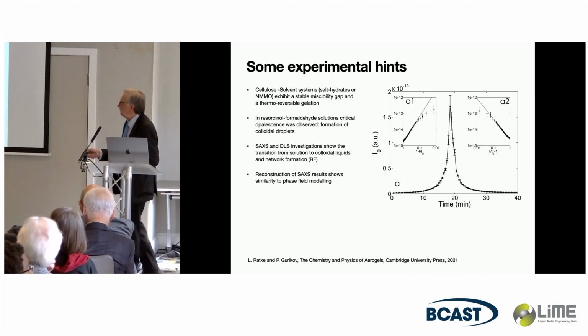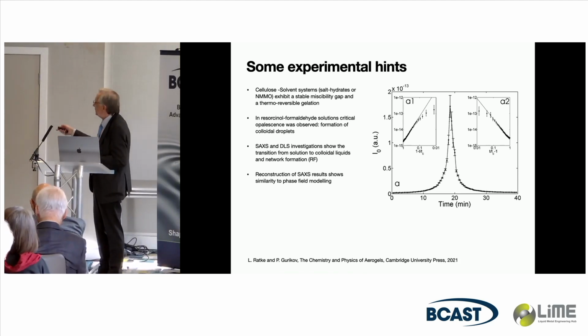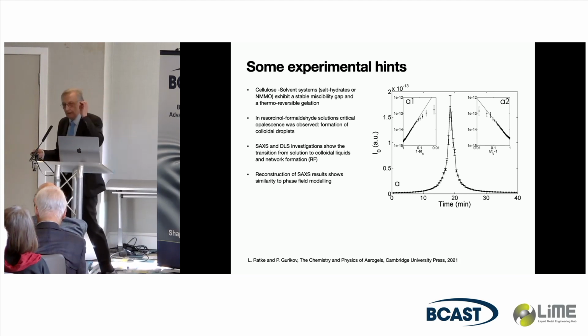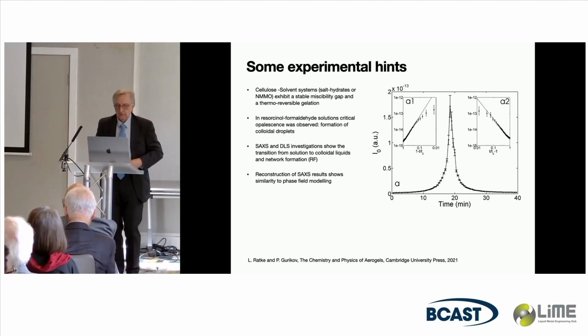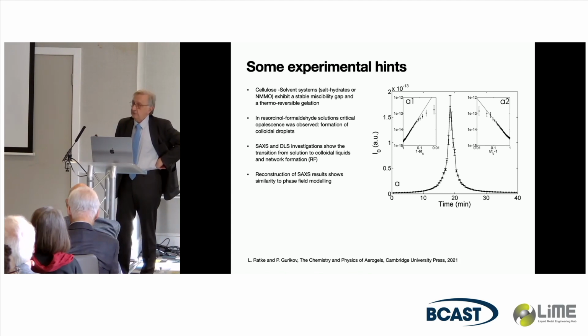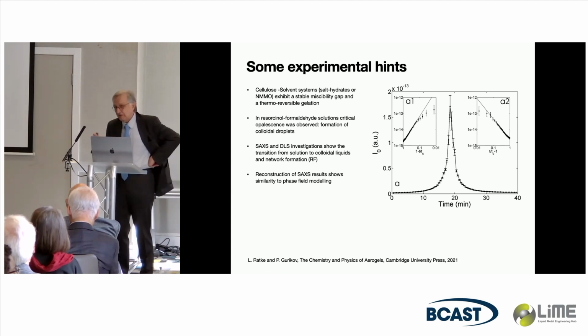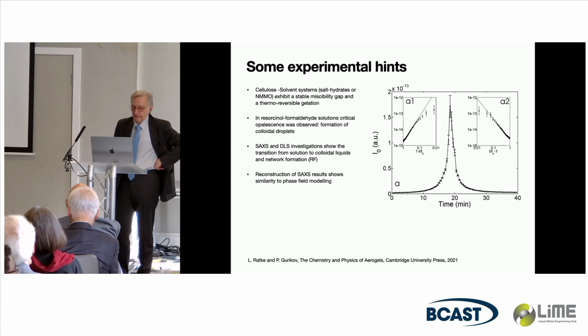And you measure the scattering, in this case X-ray scattering, and measured this critical opalescence, showing this could be formation of colloidal droplets as we had it. And said, well, now they must become wet gel droplets and then do everything else.